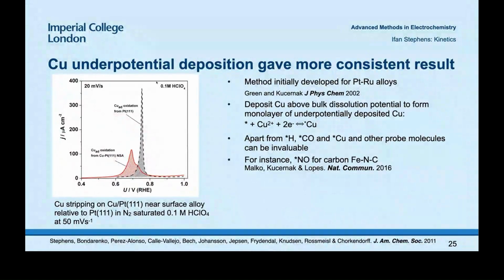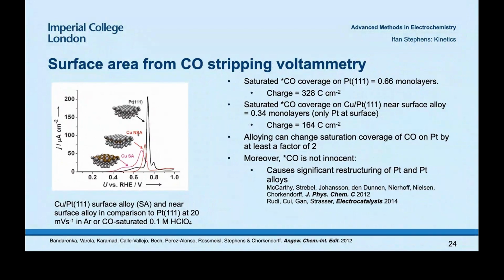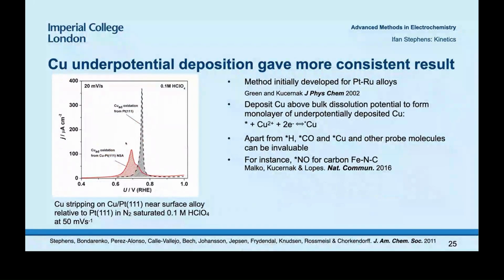Another method we found, on the same copper near-surface alloy as the single crystal, worked better: a method that Anthony Kucernak had developed, originally for platinum-ruthenium alloys. What you do is essentially electrodeposit copper above the bulk dissolution potential, in what's called an underpotential deposition. So you deposit up to a monolayer of copper, and you won't deposit much more than a monolayer because you're not at the potential where bulk copper forms. And then you desorb the copper and measure the stripping charge. We found that this gave more consistent data than actual CO stripping.